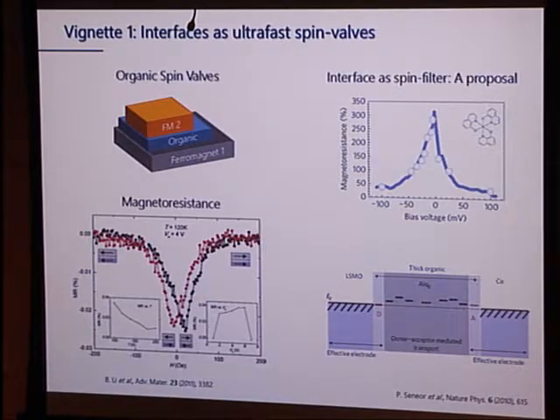So the first vignette that I want to tell you about is the notion that perhaps we can think about spin as a quantity that we want to understand at an interface. This is driven by the idea that you can make things called spin valves with organic materials. Those have been demonstrated, it's probably about 15 years now since the first organic spin valves, and their generic layout looks like this. You have a ferromagnet, an organic active layer, and a ferromagnet. The reason to use organics is because they're made of carbon, nitrogen, oxygen. These all have low nuclear charge. That means that spin orbit coupling doesn't play a big role.